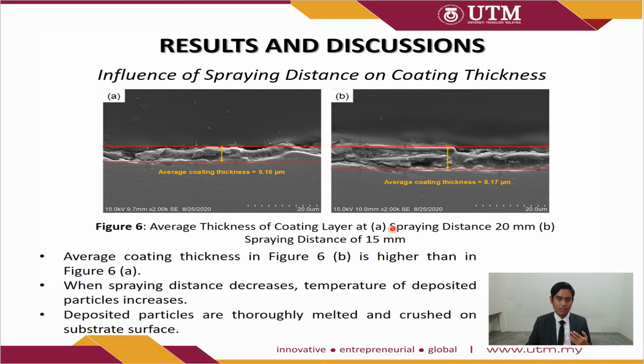This is because when the spraying distance decreases, the temperature of deposited particle will increase. As a result, the deposited particles are thoroughly melted and crushed on the substrate surface. However, when the spraying distance increases, the temperature of the sprayed powder particle will decrease before they are being deposited on the substrate surface, therefore resulting in partial solidification. Consequently, a thinner layer of coating will be formed.